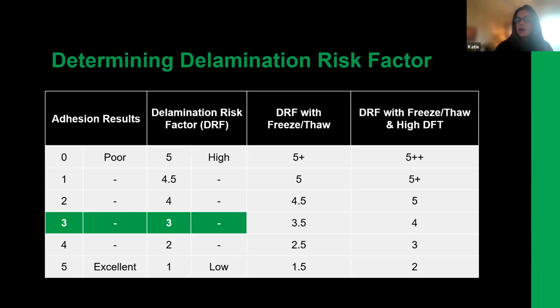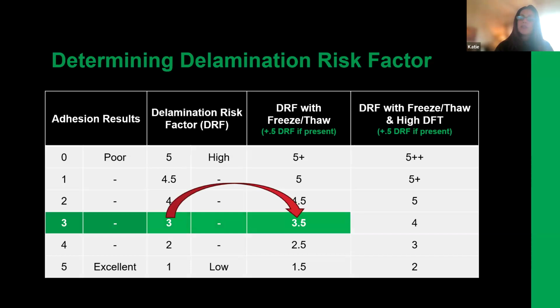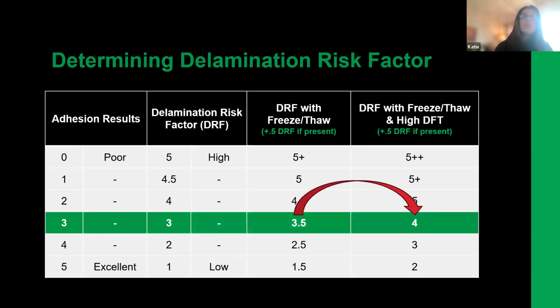But now we need to take into account the geographic location. Let's say we're in an area that's going to experience some freeze-thaw cycles throughout the year. That's going to take us from our 3 to a 3.5. That's added stress. It is going to increase our delamination risk factor. Now, what if we're going over a system that has a high existing total film build, say 15 plus mils? That's going to take us from our risk factor of 3.5 to 4. So that factor is important for determining our coating options and our compatibilities. So remember this number 4 because we're going to use it.